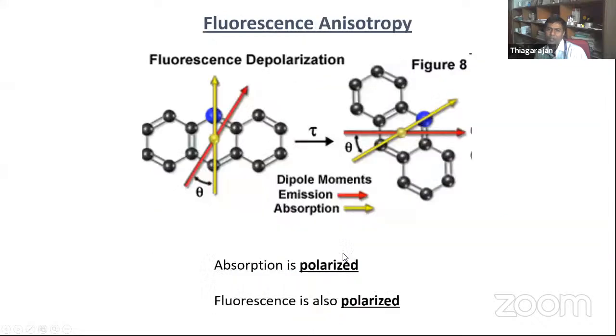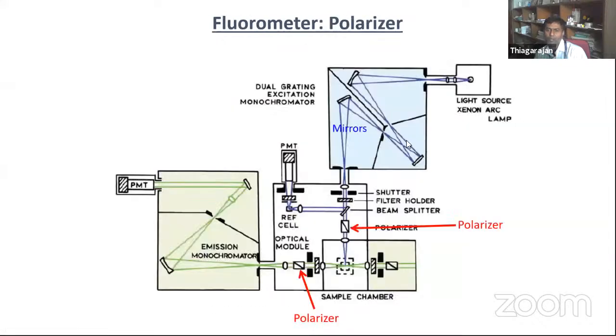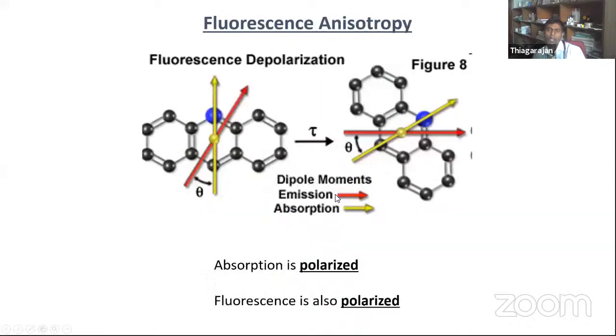Polarizer is especially for biomolecules. People always use the polarizer before the excitation as well as after the emission. This is the sample, this is the excitation, and then here the emission. Before the detector, we use the polarizer. Before the excitation, we can also use the polarizer. So the light is otherwise non-polarized. For example, if we use a laser source, it is always polarized, but the xenon lamp light is non-polarized.